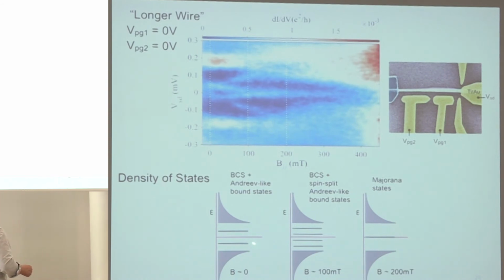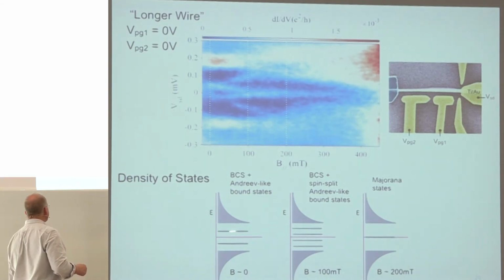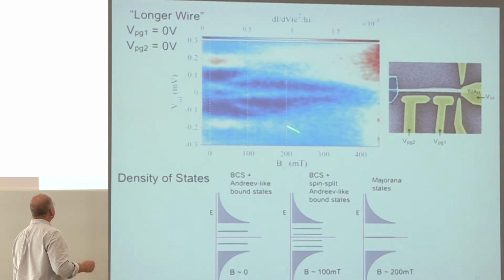Here's a model of that picture, which is a BCS density of states, with two levels that appear below the gap. Those levels are probably associated with some bound state within the system. Those states split when the Zeeman field is applied. One of them goes up, one of them comes down. They meet in the middle and form this, I would say, Majorana state that lives at zero energy above a high magnetic field. And there it is right there.